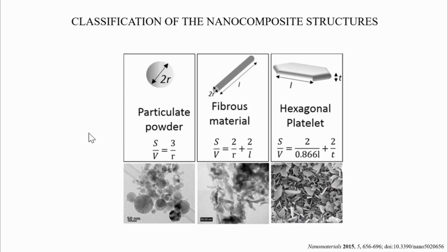The changes in particle diameter, fibrous material diameter, or layer thickness from micrometer to nanometer change the surface area to volume ratio by 1 or 2 orders of magnitude. This means that with the drastic increase in interfacial area, the properties of the composite are more and more dominated by the properties of interfaces.